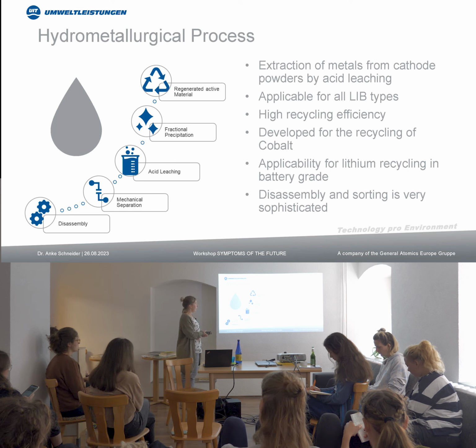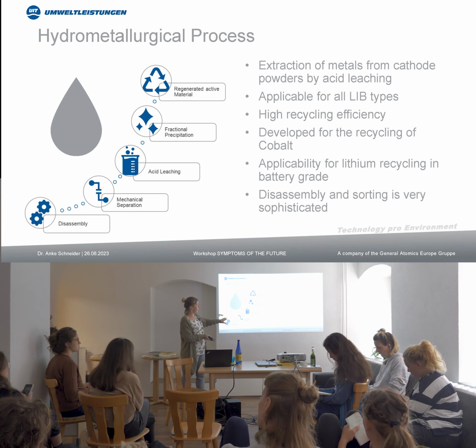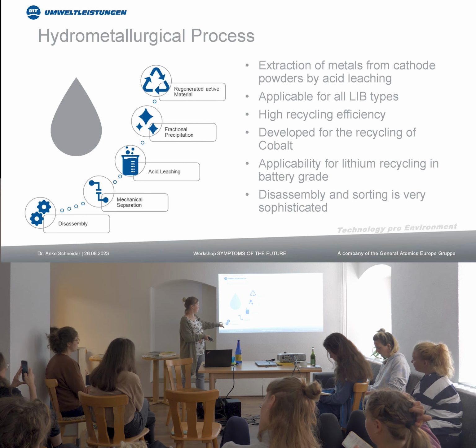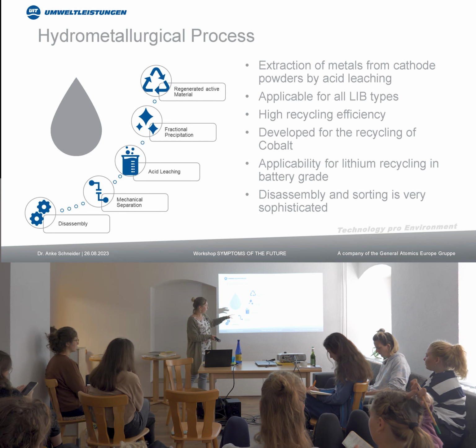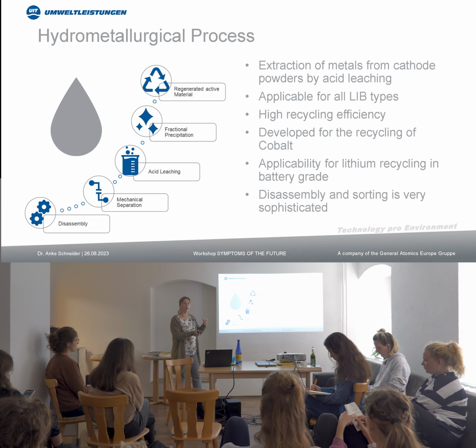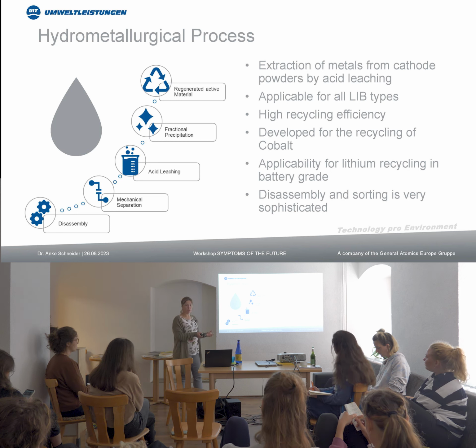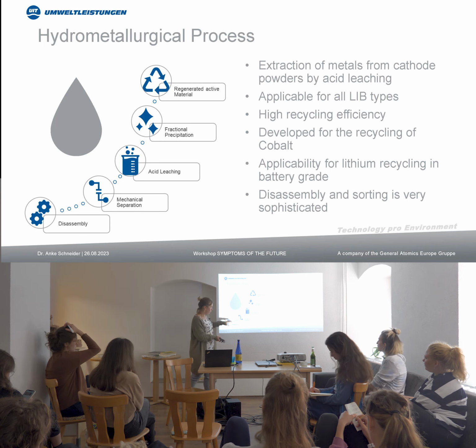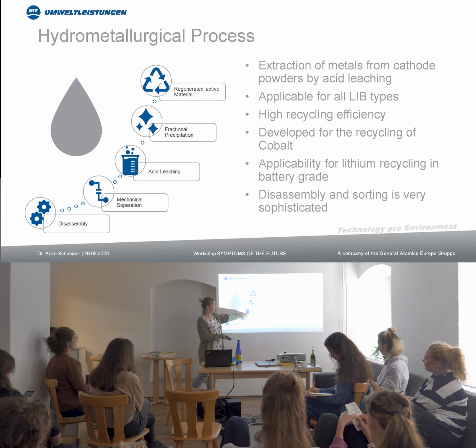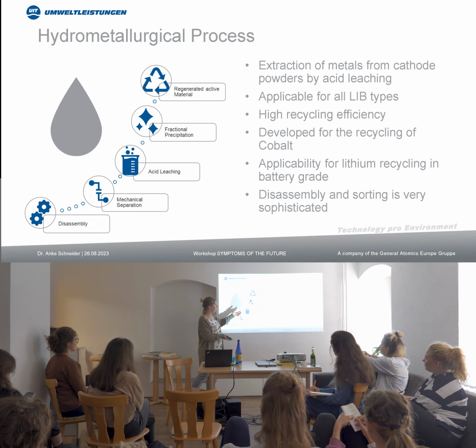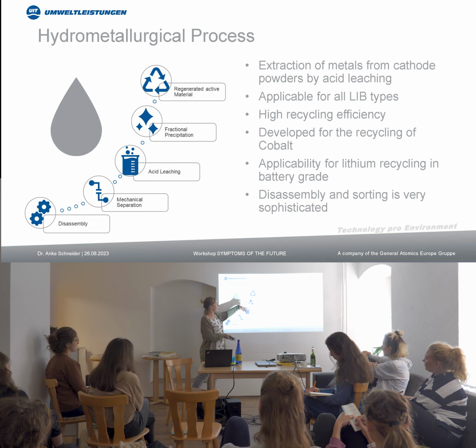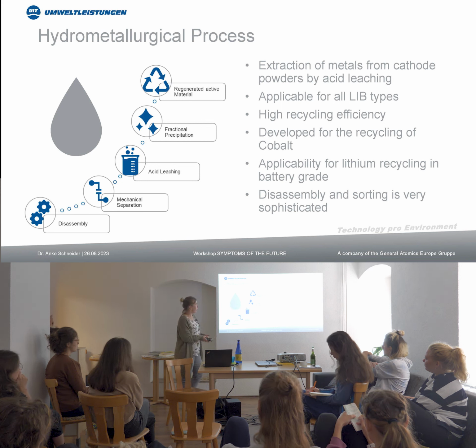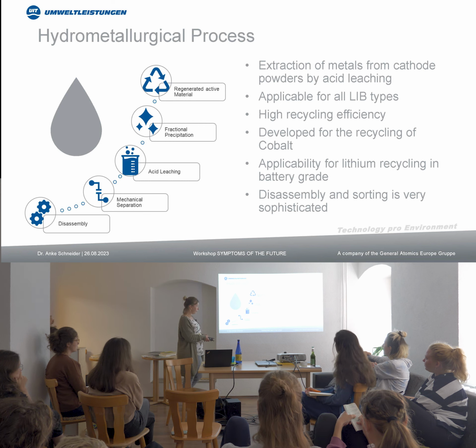Yes, and last but not least is the hydromet process. Again, here we start with a challenging disassembling. However, as soon as we have our material, it doesn't need to be as pure as for the direct recycling. We can leach it also with acids, so it's similar to the pyro process. We have it in solution, we can precipitate the material and produce regenerated active material.